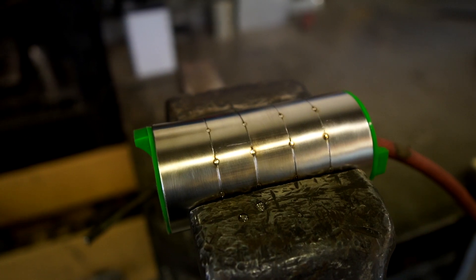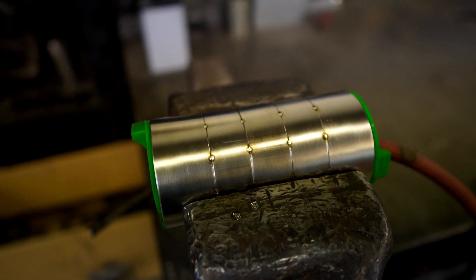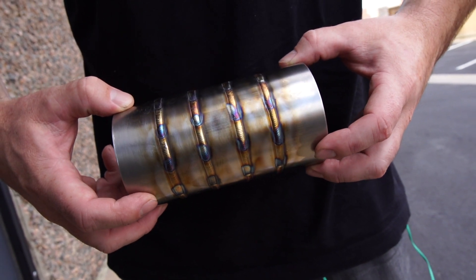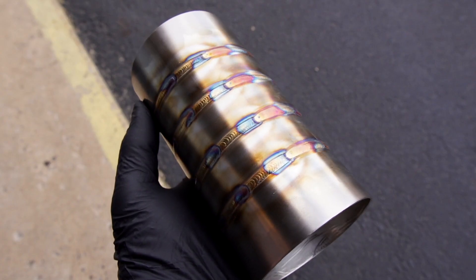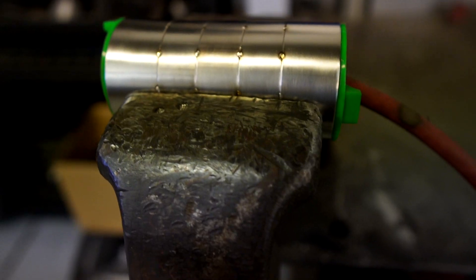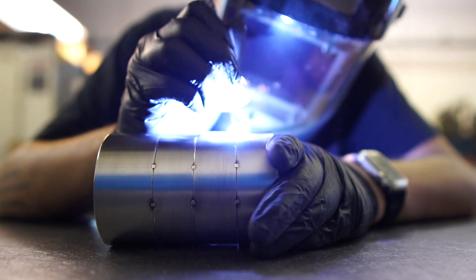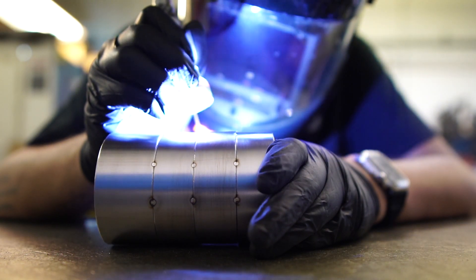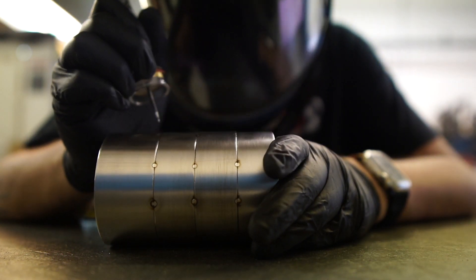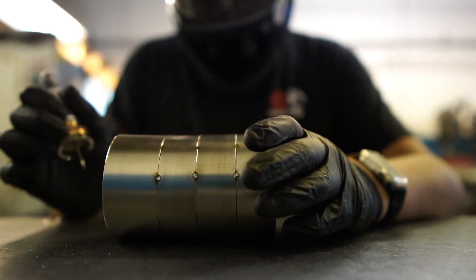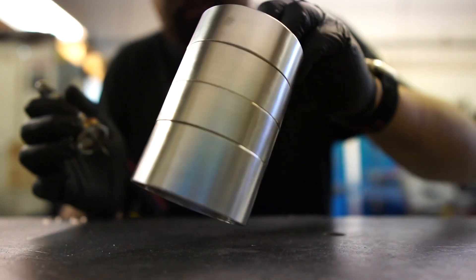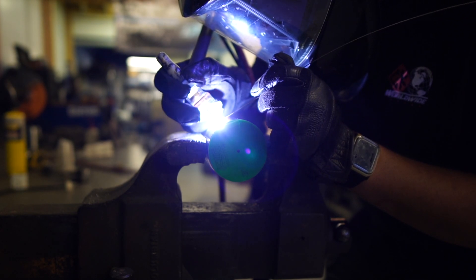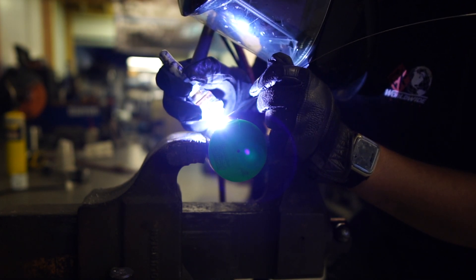If you are just welding one joint, the only crucial thing about tack weld placement for me is just making sure that I have enough tacks on my part and all of my gaps are closed. I usually tack every inch or so depending on diameter and how far I'll be running. If you are welding pie cuts, you can align all of your tack welds so that all of your starts and stops line up real nice and your oxidation profiles look even and symmetrical. The easiest way to be consistent when welding is comfort and repeatability. Make sure you have a place to rest your hand and take a few dry runs so you know you're comfortable and ready to weld.